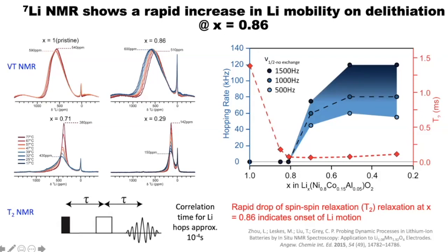And a more sensitive way of looking at this is to look at the so-called spin-spin relaxation, or T2 time. And this is work with Katarina's, where by quantifying how fast the lithium ions move in the time scale of this measurement, which is about 100 microseconds, you can again look at the onset of lithium mobility that's happening at about 0.86, or just before 0.86. So the point is you start to get rapid lithium mobility as you start to pull lithium out of the structure.